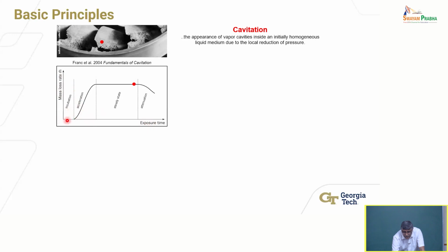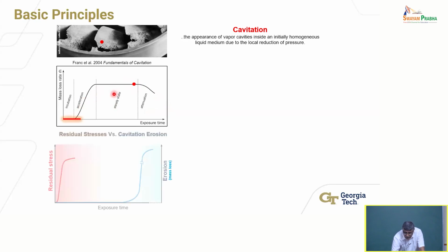Initially, there's some incubation time. It takes some finite amount of time for these bubbles to produce enough strain in the material to cause it to deform plastically, and then once you strain it all the way past the elastic limit to the fracture strain, it'll fail and start eroding. So it takes some time. There is an acceleration period and a steady state, and then eventually it'll attenuate. So this happens. Now, how do we take advantage of this? This is the basic principle. So how do I use it to generate residual stresses?